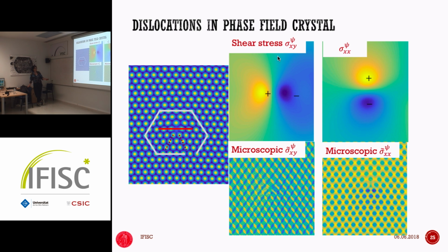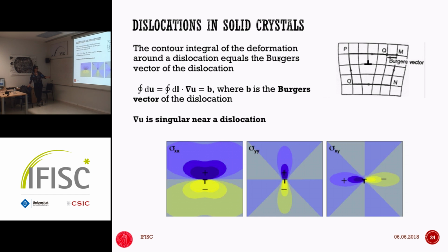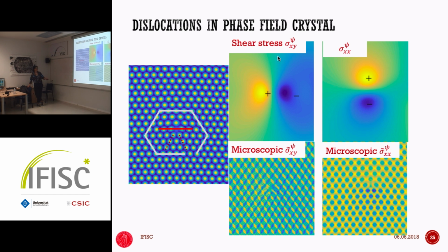So in the phase-field crystal, we have a dislocation in this case, and it's a little bit more complicated in the sense that we insert 2 planes. You see the planes coming up here, and then on the other side they are disappearing. So we have these 2 extra planes that are inserted up to this point and not beyond. That means we're going to have a compression stress here and an extension stress there. All right? And you can also look at the shear stress, and you see this shape here. But if you look at the microscopic stress, you see that it kind of localizes the stress. You see that there's something going on here, but because of the microscopic oscillations, it's hard to visualize the stress localization, but definitely upon coarse-graining, they come out very nicely.